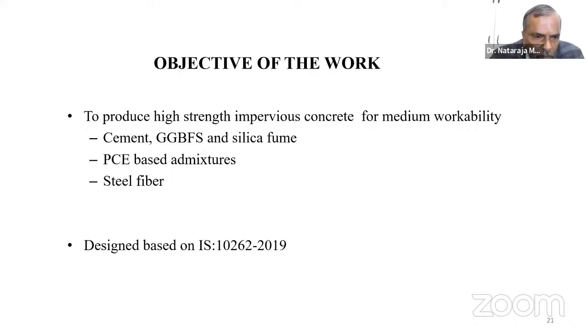I'm just taking one combination of supplementary materials. I have used GGBFS to the extent of 50%. Silica fume, without silica fume, it is not possible to produce high strength concrete. Otherwise, you may have to use metakaolin to the extent of about 10 to 15%. So 65% of supplementary materials and only 35% of cement we have considered here to produce concrete up to M100.